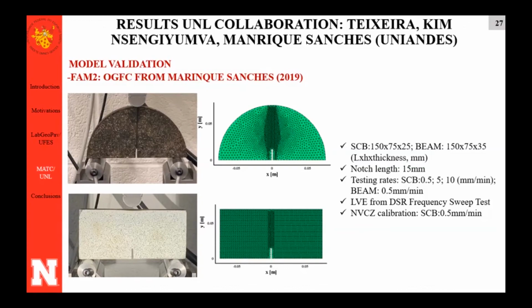So here are the geometries that she used for SCB: 150 millimeter diameter with 75 radius and 25 millimeter thickness. And the beam sample was 150 millimeter length, height 75 with 35 millimeter thickness. Both samples have a 15 millimeter notch length, right? And she tested the SCB in 3 rates, and she tested the beam in 1 rate.